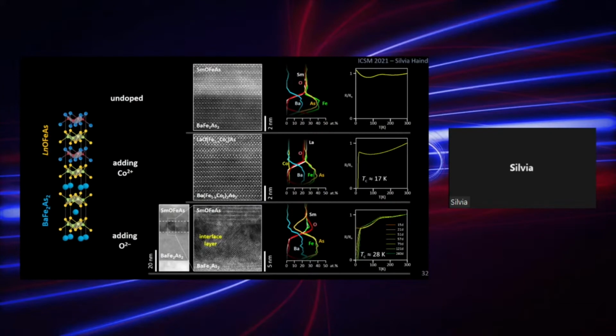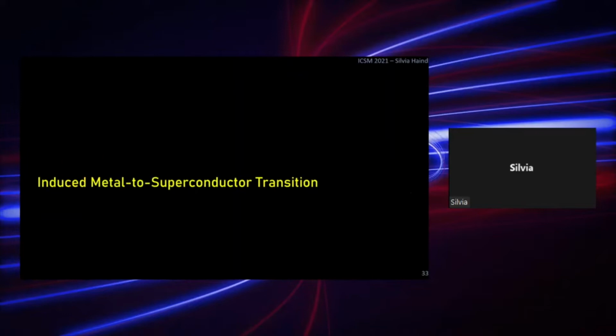You can see that clearly also in the Auger electron spectroscopy depth profile, where we have a strong decrease in the arsenic content, and we have basically all the additional oxygen, and the oxygen imbalance is swallowed up by the interface layer. Interestingly, this bilayer with this interface layer shows an induced metal to superconductor transition with a quite high superconducting temperature of 28 Kelvin. So let me just say a word about this induced metal to superconductor transition, which is now under investigation.